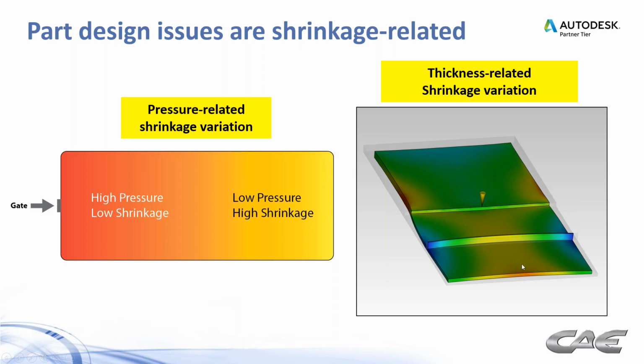So it tries to bend this part in the opposite direction. So you can see why it's often stated that you should maintain as uniform a wall as you possibly can. But this really illustrates how differences in thickness change the shrinkage of your part. And don't forget, when you're cutting steel to typically one shrinkage number, in fact the material shrinks at a bunch of different numbers throughout the part. So we have to be mindful of how the different part thicknesses play in relation to the shrinkage you've selected to cut your steel to.